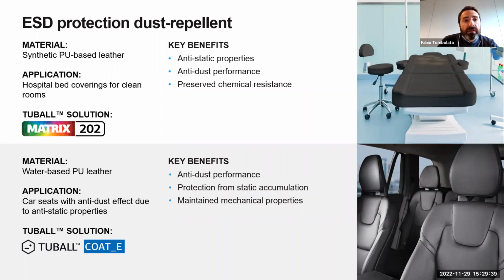ESD protection and anti-dust properties can be achieved by combining polyurethane chemistry together with our TUBALL MATRIX. Here you see two examples. Application: hospital bed covering for clean rooms. A synthetic PU system was modified with MATRIX 202 to achieve anti-dust and anti-static properties, maintaining the chemical resistance of the material unchanged. Just to give you an idea, in this specific case, a surface resistivity in the range of 10^6 to 10^8 was achieved.